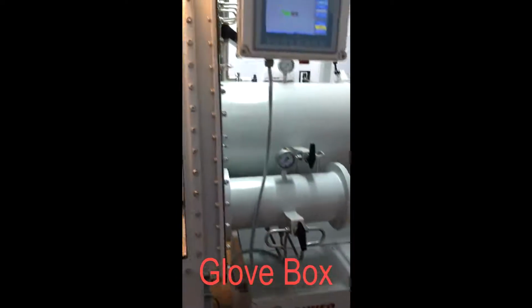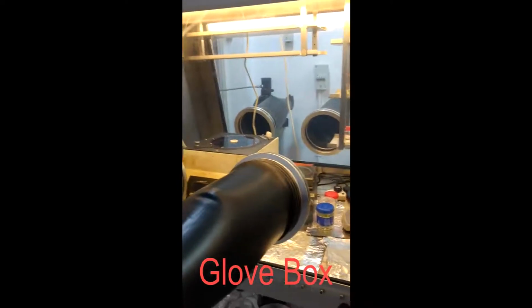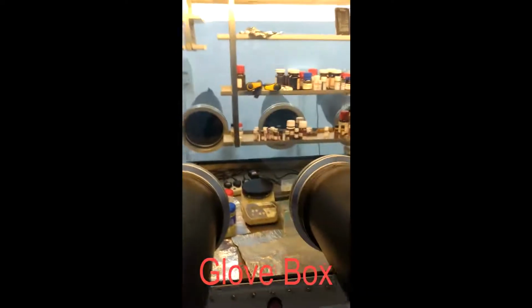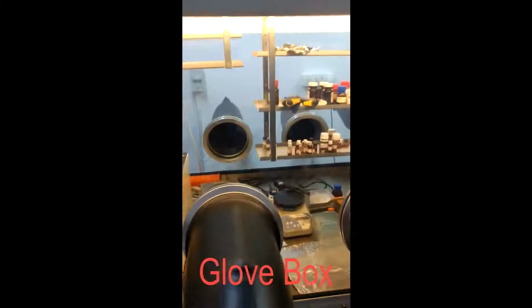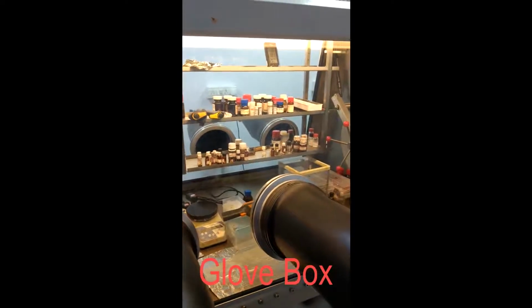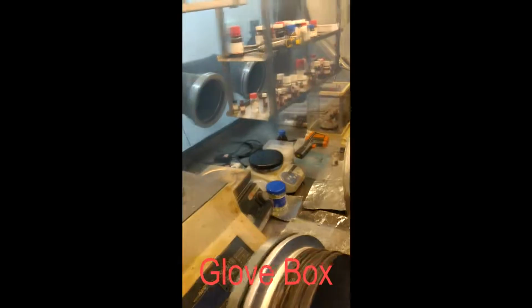We have a dual chamber closed loop circulation and purification system which helps to maintain the oxygen and moisture ppm below 1 ppm. As you can see, we have 8 glove ports, which means that we can have 4 people work in the glove box simultaneously. You can also see that inside the glove box we have a weighing machine, a hot plate stirrer, and a spin coater which is used for fabrication of thin films from 20 nanometer to 100 nanometer range. The carrier gas for this glove box is generally nitrogen or argon, which is used to flush the box all the time.